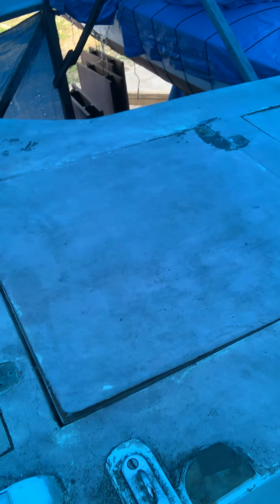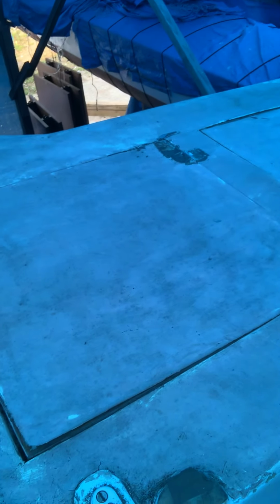But to go here into a bit more important detail in the grand scheme of things, looking at this beam, you can see 1, 2, 3 lockers, and to the casual onlooker, this would seem like a great thing. Yeah, you've got lots of storage. Woohoo! No problem. Get in and out of them. The problem is that these are way, way, way too large, and the designer specified a much smaller opening for a Danforth 12H anchor for a wet locker on both sides that is heavily glassed and properly maintained. And as you can see, of course, these were not.